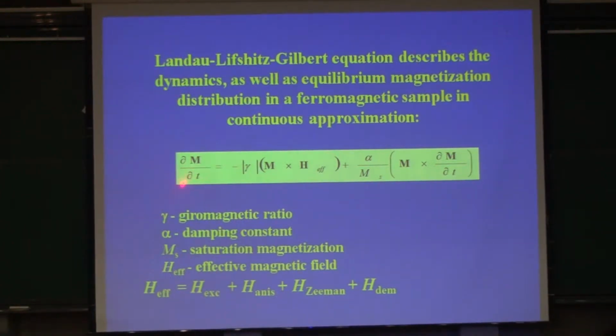And the main idea is that the phenomenological equation for the time-dependent dynamics of the magnetization should depend on the first term, which is actually Larmor precession, some kind of cross product. However, you also need a damping term. Otherwise, your magnetization cannot relax to the field direction. This is the angular-momentum-preserving rotation, but you need one damping term. And this is the only way you can get the Landau-Lifshitz equation. This is a phenomenological equation, but mathematically you can prove this is the only possible form.